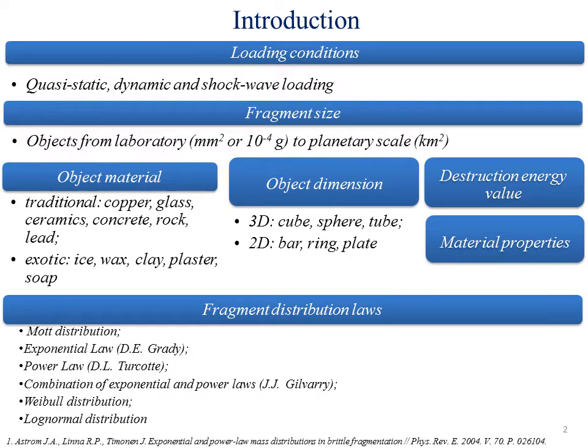The fragmentation process exhibits the signs of a critical phenomenon and corresponding scaling laws. The analysis of the material behavior is carried out depending on the load energy near a certain critical point, which corresponds to the transition from a damaged material to a fragmented material. The critical behavior in fragmentation is investigated by analyzing statistical fragment distributions depending on the material properties, ductile, brittle, its initial structure, porosity, load intensity.